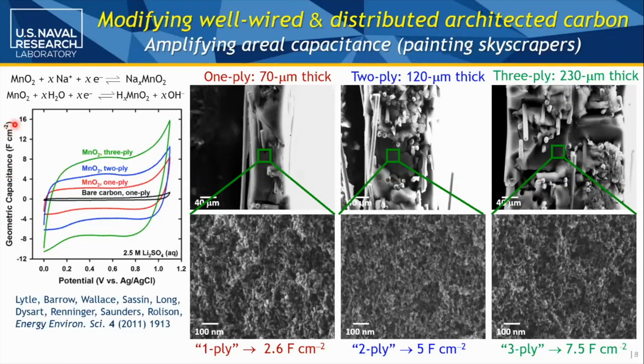Our current is now the capacitance normalized to the area of the system. We can also look at it as normalized to the mass of MnO2. And as you would expect, if we've got this kind of control, the per mass comes out to the same number because we've got, if you will, 3 plies, much more thickness. On a per area basis, you've upped it, but per gram, it looks identical. So particularly for areal footprint specific applications, this is the kind of control you want. You want to build up as a skyscraper, but still have control of the ions, the electrons, and the molecules.